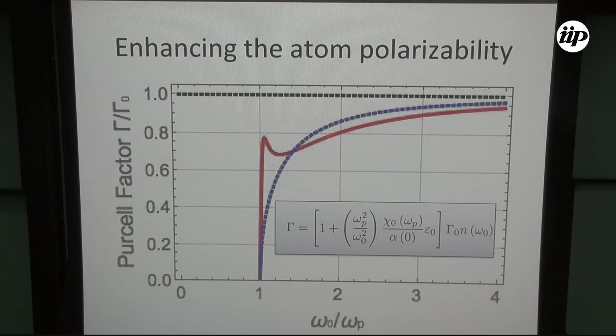And this is the plot that I wanted to show you. The Purcell factor is defined as the ratio between the spontaneous emission rate in the medium and the value in vacuum. So I would get 1 here if I were in the vacuum all the time. The blue line is without the polarizability correction, so simply gamma 0 times the index of refraction. And as we know, the index of refraction goes to 0 at the plasmon frequency. So in the medium, we would only have the decrease of the spontaneous emission rate, and 0 to the left here.